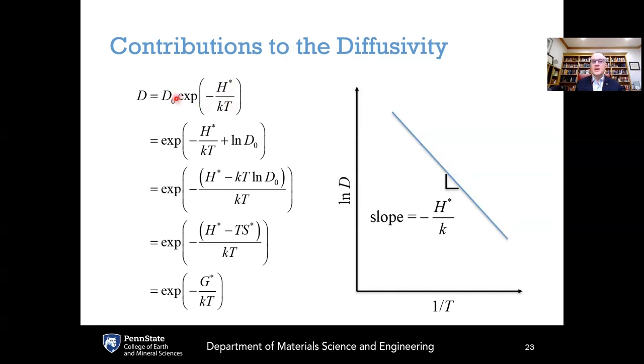One thing you can do is to pull the D0 into the argument of the exponential. When you do that, it picks up a natural log. So now you've got two terms within the argument of the exponential. And if we give this second term the same denominator as the first, that involves multiplying by minus kT over minus kT to combine the two. Now the argument of the exponential is minus H star minus kT natural log of D0, and it's all over kT. Now this looks like something.